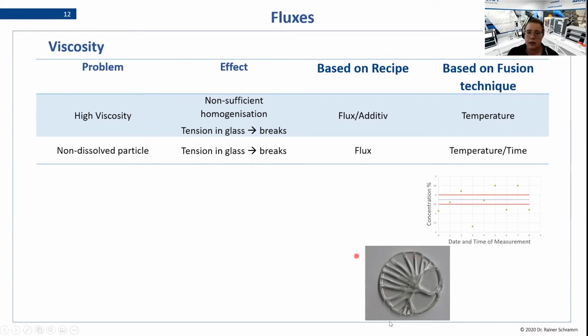The second thing how this can happen is a non-dissolved particle. There's a particle somewhere in your glass, and along that particle, the glass will just break. This is the same effect here. You have the tension in the glass and it breaks. And based on the recipe, you will have to have a look at the fusion flux that is used. And based on the fusion technique, you can as well have a look at the temperature, but also at the fusion time.